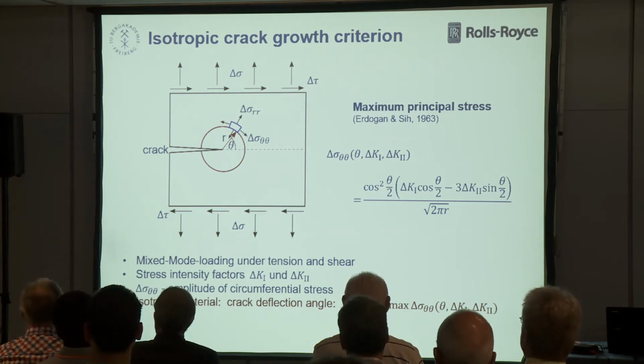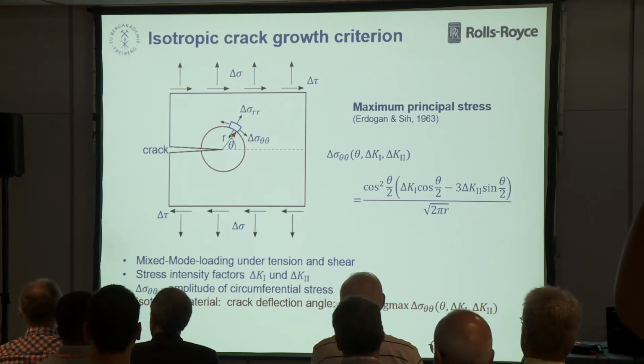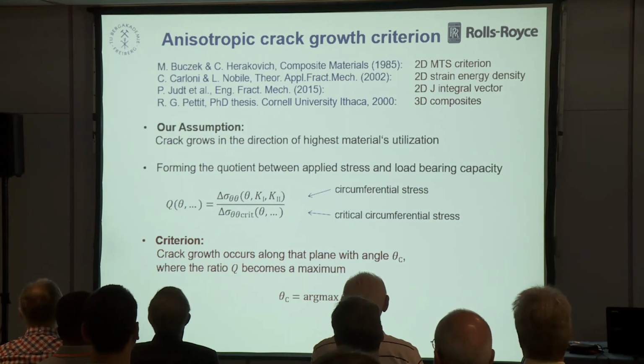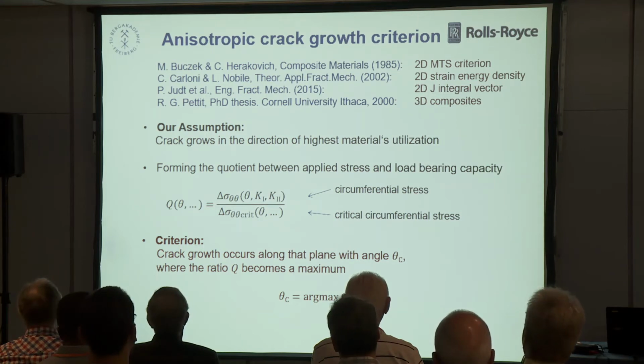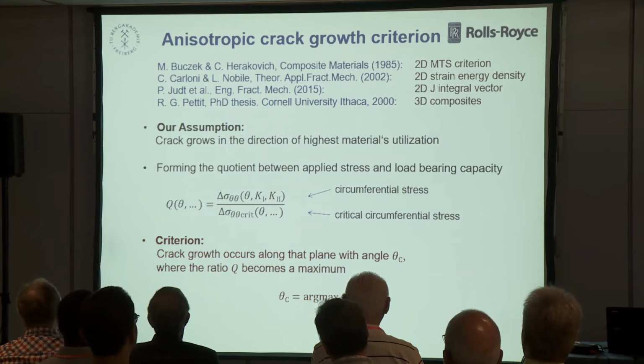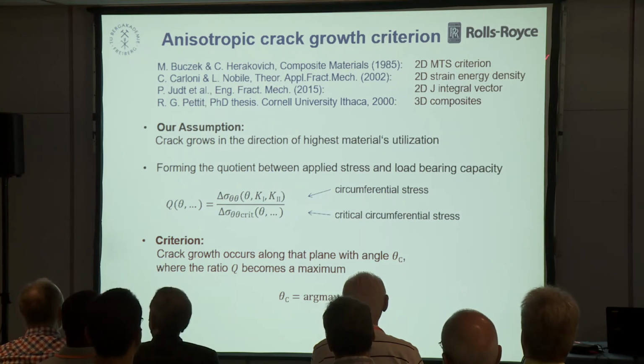Isotropic deformation behavior and isotropic crack behavior. Our material is isotropic in the elastic behavior, but not in the fracture behavior. So I looked into the literature at what has been investigated for anisotropic crack growth. It is not complete, but most work is done on composite materials. It's clear, composite materials have this anisotropy in crack propagation.